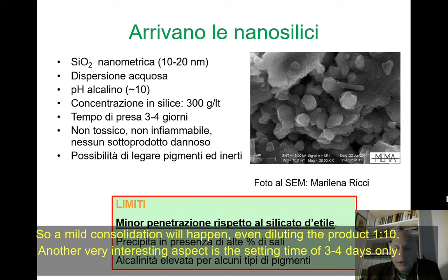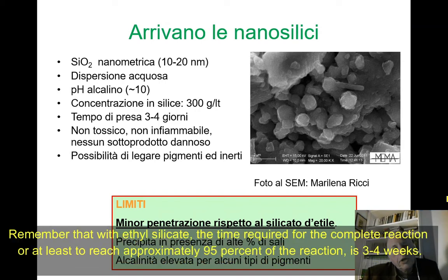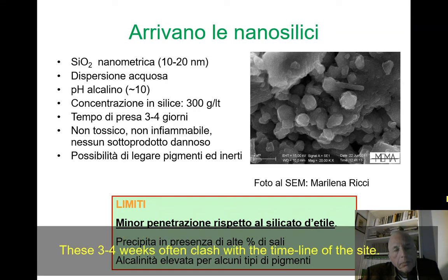Another very interesting aspect is the setting time of only 3-4 days. This allows us to perform consolidation with silica, that is exactly the same material generated by the reaction of ethyl silicate, but in just 3-4 days. Remember that with ethyl silicate, the time required for the complete reaction, or at least to reach approximately 95% of the reaction, is 3-4 weeks. And these 3-4 weeks often clash with the timeline of the site.